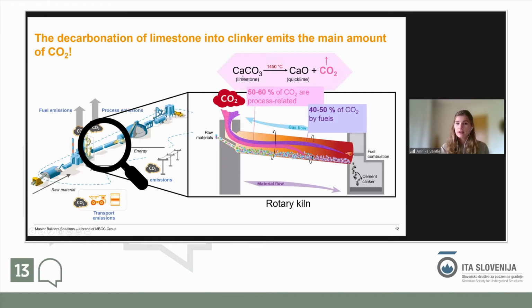So for every molecule of calcium oxide you also have one molecule of CO2. And this is something that you cannot avoid. So if you want to have clinker as a binder, which is I would say the best binder we have or we know, then you cannot get rid of these emissions. These are just there.